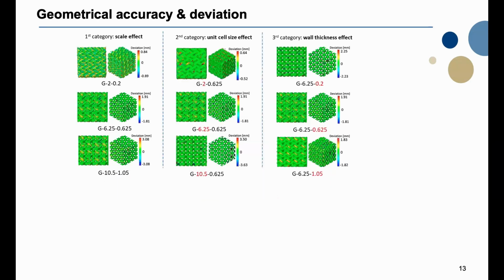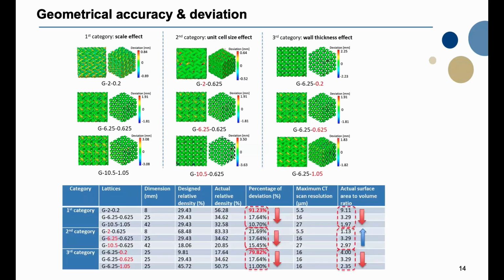All the geometries went through CT analysis, and we can see, for example, for the scale effect, as the scale increases, the percentage of deviation also decreases a lot. If you look at the numbers here, this is the lattice with the smallest dimensions, and it has a huge percentage of deviation.